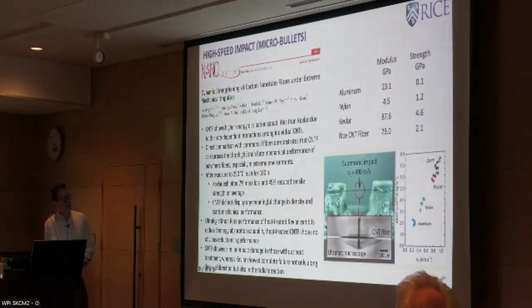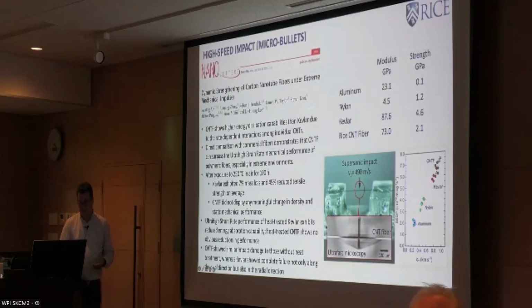Some of this is being explained. This is work by Jae-Hwang Lee at the University of Massachusetts, who shot micro bullets at one of these fibers and compared to aluminum, nylon, and Kevlar. Kevlar especially is known for being a ballistic fiber. And what he saw when he looked at the ballistic behavior is that the carbon nanotube fiber was better than Kevlar, even though on quasi-static pulling, in terms of strength, the carbon nanotube fiber is only about half of Kevlar.